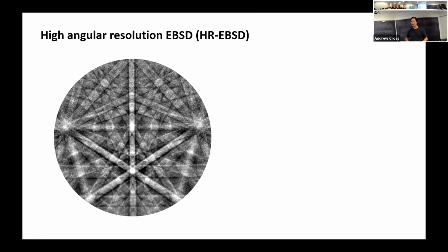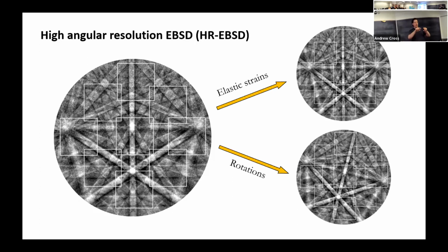In this case, instead of just fitting a solution to our pattern and then throwing the pattern away, we're going to store all of the patterns for our maps, and pick a reference pattern for an individual grain. We're going to draw a bunch of regions of interest on that pattern, and then cross-correlate our reference pattern with all the other patterns in the grain for each region of interest. Doing this, you can resolve things like rotations and also elastic strain. It's kind of hard to see here, but the electron pattern has been squished along the horizontal axis. This will get you up to about a two order of magnitude increase in angular precision, so you can resolve really tiny changes in crystal orientation.